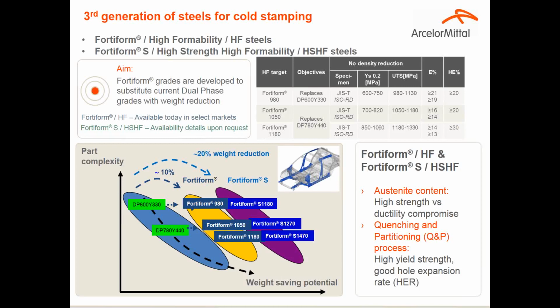The Fortiform S grades, which is the high strength, high formability grades, through the Q&P process, or the quenching and partitioning process, availability details can be shared separately, but from a product design standpoint, both these grades introduce new opportunities for lightweighting. The Fortiform HF grade series allows an additional 10% weight savings potential versus the competing current grades, and the Fortiform S will allow an additional 20% lightweighting opportunity with this product family.